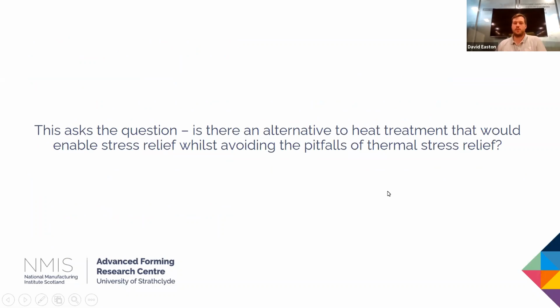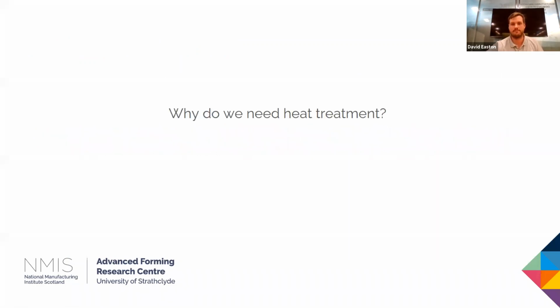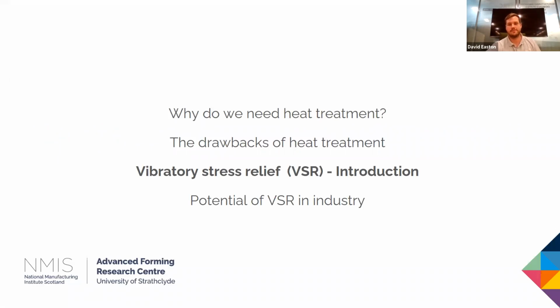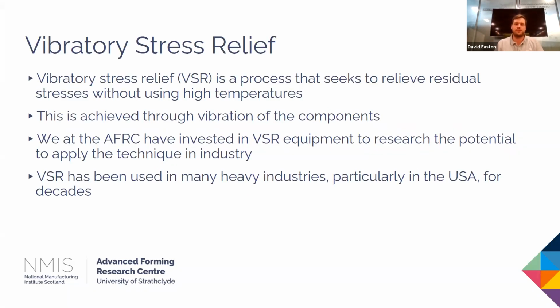So all of these together ask the question, is there an alternative to heat treatment whereby we could get benefits? We could remove the residual stresses or reduce the residual stresses whilst avoiding some of these pitfalls of traditional thermal stress relief. The answer, potentially, is vibratory stress relief. So vibratory stress relief, or VSR, is a process whereby we look to remove residual stresses from a component without elevating the temperature at all. And the way that we do this is through the vibration of the component.